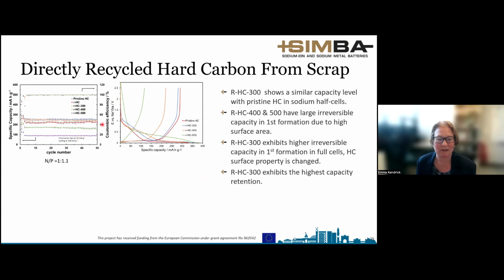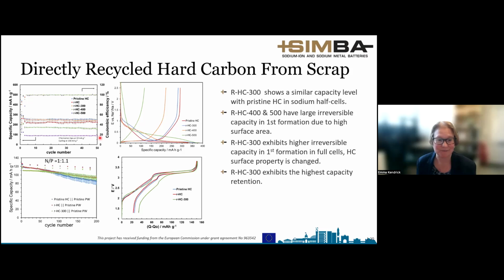This is the hard carbon in a half cell. We've got some good cycle life of the pristine, which is in the blue, and the reclaimed, the 300, are cycling pretty well. In fact, the 300 is as good as our pristine. Whereas if we go higher in temperature, we end up with a much higher surface area. We also get higher first cycle loss and also lower capacity when we cycle it.